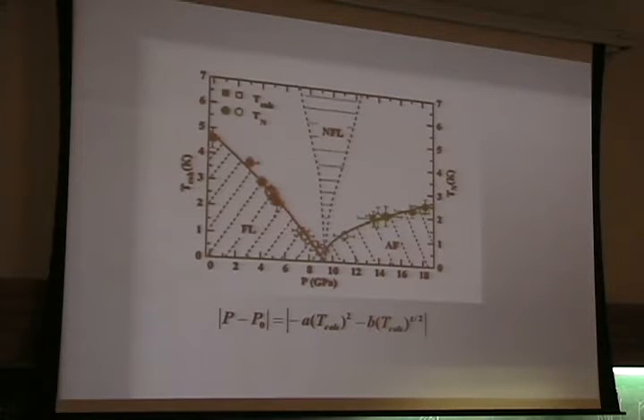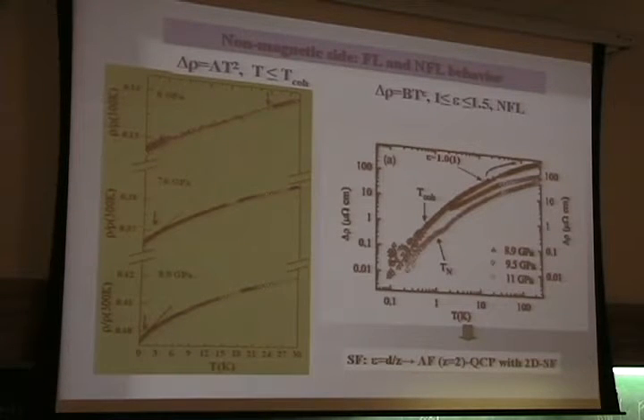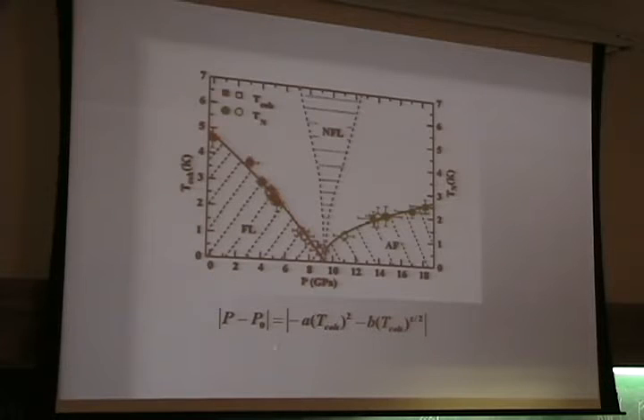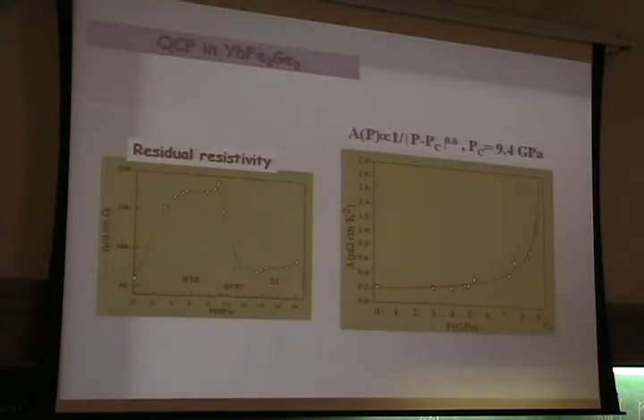Okay, so when you make the diagram, we see that the coherence line is dominated by a linear behavior. Okay, and if you try to get the exponent of this coherence line, we see that it is the linear term. If you relate it to this kind of scaling, the linear behavior is dominated by this linear term. That means that zeta must be equal to 2, that is the case of an antiferromagnet near a 2D spin fluctuation model near the quantum critical point. Okay, and this is the antiferromagnetic line, and this is our phase diagram for this system.